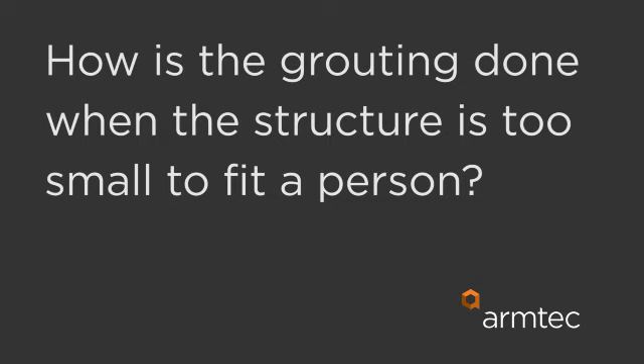How is the grouting done when the structure is too small to fit a person? Well, there's various ways to do that. Actually, I was on a call the other day about that. It was a 24-inch pipe that was being relined, and typically what the guys do is slip line, bulkhead up the ends, and then cut some small holes in behind the bulkheads and pour the grout in through the host structure. Now, if it's really long, you can do one at each end, and of course you're not going to excavate the road or anything, but yes, cut a hole in the host pipe after you've built your bulkheads to keep the grout in, and then just either pump or flow the grout in.